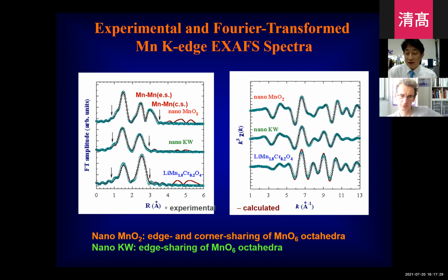The second peak corresponds to the edge sharing of the manganese bond distance. But the third peak corresponds to the corner shared Mn bonding pair. So in case of nano MnO2, as we guess from the EXAFS, there's the edge sharing and corner sharing. In case of the nano KW, there's only one manganese peak corresponding to the edge sharing. So based on that, we can guess the nano MnO2 is composed of the edge sharing and corner sharing of the MnO6 octahedra. But in case of nano KW, it is composed of the edge sharing of the MnO6 octahedra.